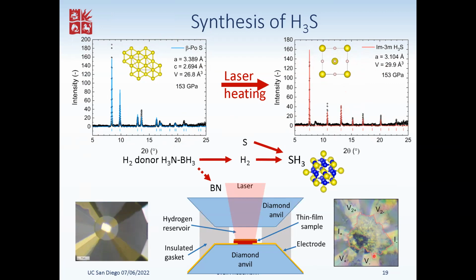This is the sample for this particular X-ray measurement. What we've got here is in fact 6 electrodes, so it's not exactly the same sample as this one. We've got 6 electrodes for redundancy, but also it allows us, as I'll show in a minute, to probe the sample in a bit more detail.